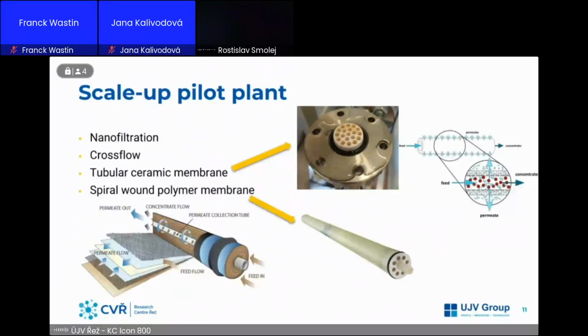So the ceramic membranes should withstand more aggressive environment, like I said, low, high pH, and also the radioactive environment, but they are not that well established. They're not that well used, so we don't know that much about them. On the contrary, the polymer membranes are very widely used, but their resistance to the aggressive environment is not as good as the ceramic one.